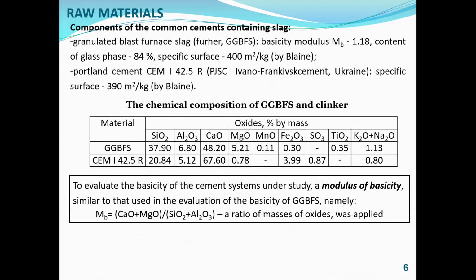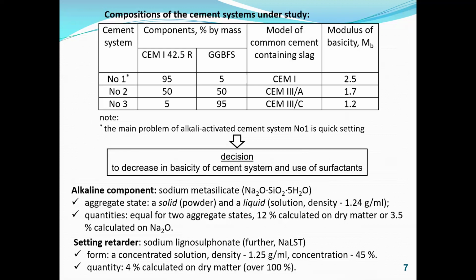Raw materials: granulated blast furnace slag, as well as Portland cement, CEM I 42.5R, were used as basic constituents of the common cements containing slag. To evaluate the basicity of the cement systems under study, a modulus of basicity as a ratio of masses of oxides was applied. Used in the study were three cement systems, the compositions of which are given in the table.